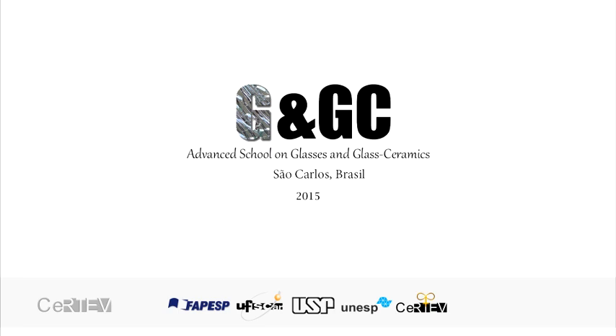So silica is a good glass former or network former, because I shall use this term again and again. So you should have a clear idea about the network former. Similarly, for phosphate glass, here also PO4. P, phosphorus, is surrounded by 4 oxygens at the tetrahedral corners, and phosphorus is at the center of the tetrahedron. And in fluoride glasses, this distribution is very complicated. And this type of structure is generally described by a continuous random network, because all the structures, the silicon oxide bonds, forming either sharing corners or sharing edges, span the whole network.